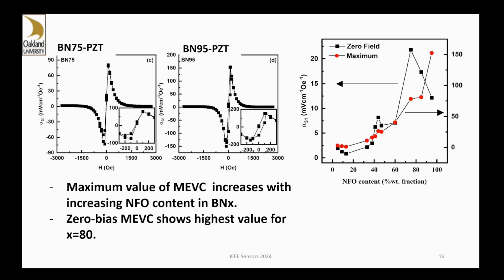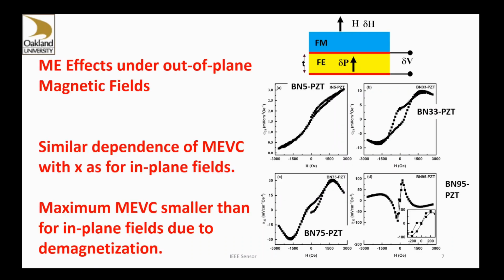And these are even higher nickel ferrite compositions: 75, 85, and 95. So what we plotted here is the overall voltage response at zero field as well as the peak values. And both of them show a maximum at around 80% of nickel ferrite. And these are the similar data for all the fields perpendicular to the plane. And once again, you see the zero bias voltage response for all these compositions.